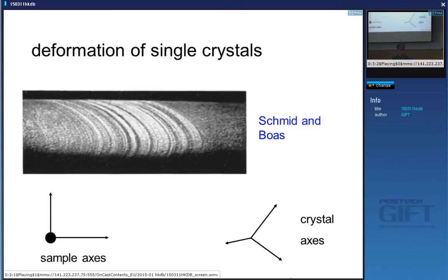Okay, now we can represent the deformation of either single crystals or polycrystals on a stereographic projection, and we can determine from that which slip system is going to operate first, even when you have 24 possibilities. So in a cubic crystal, let's say an FCC crystal like austenite, there are 24 possible slip systems. You know, there are four different close-packed planes, the 111 planes, and within each close-packed plane there are three close-packed directions, which are the 101 directions. So 4 times 3 gives us 12, and then you have the opposites as well. So there's 24 possible combinations of